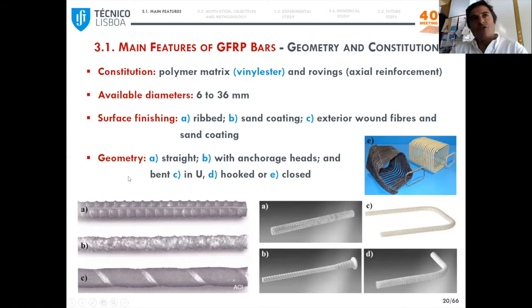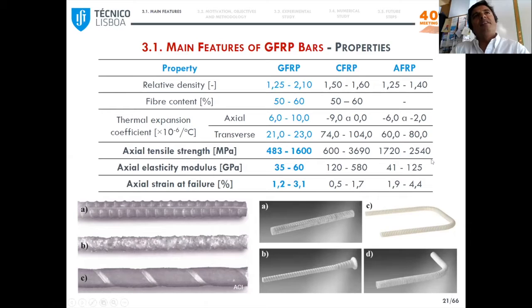In terms of geometry, they are available as straight bars, that you can see here, and bent bars with different shapes, hooked, U-shaped, and closed stirrups. Here you can see ranges of variation of different engineering properties. I highlighted those for glass FRP because they are the most often used. So the tensile strength generally is around 1000 MPa, so twice that of steel. The problem is the elastic modulus, which is around 50 GPa, so 4 times lower.